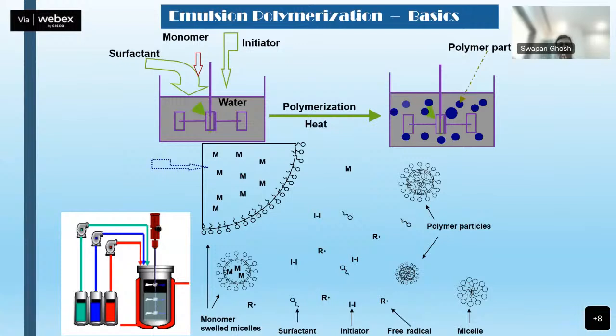If you look at the number of monomers, the number of centers, the micelles that we have created, and the amount of initiator available for the reaction, the chance of one monomer to get a radical is only 50%. So the polymers which will be made will be of different molecular size, and particle size will be different. There are certain ways we can control that so that we can have a very uniform molecular distribution and polymer particle size distribution. We can create similar sorts of particles.